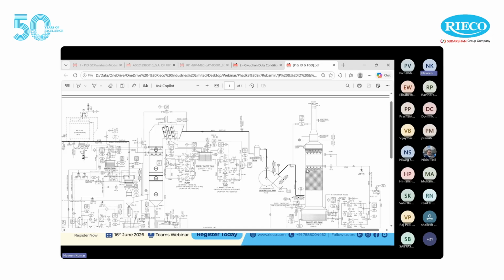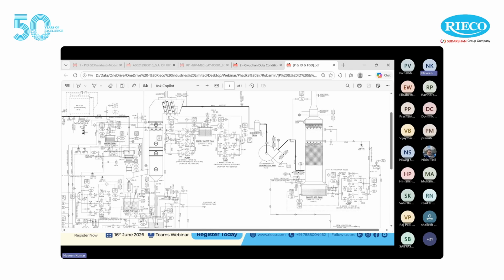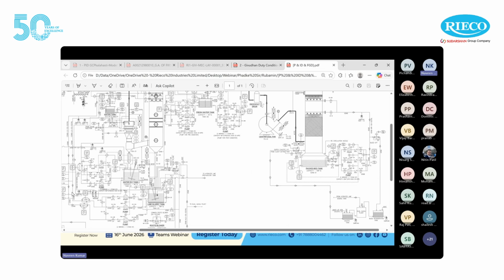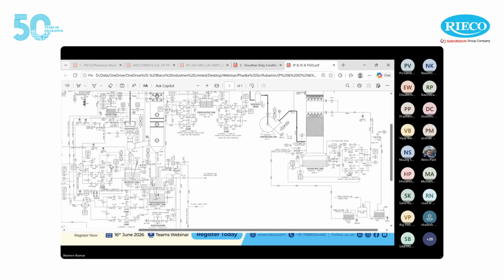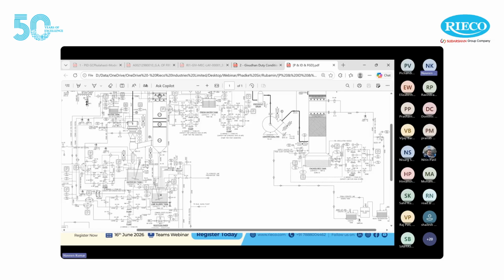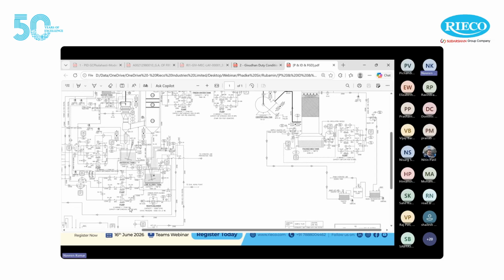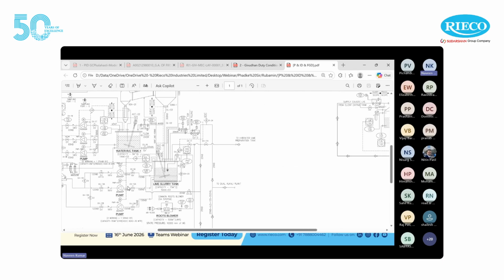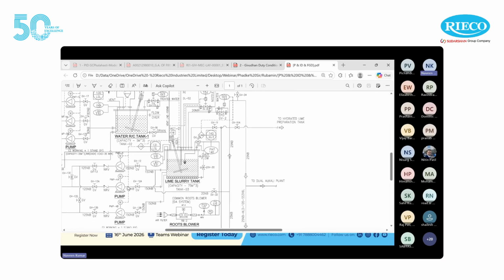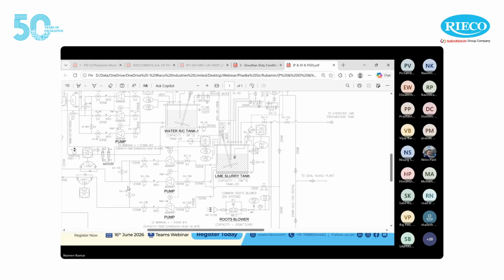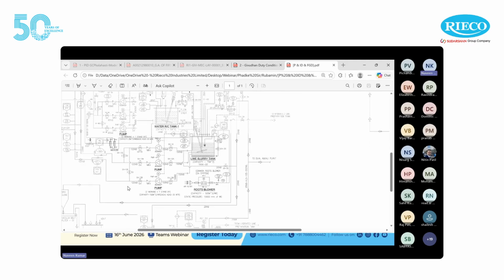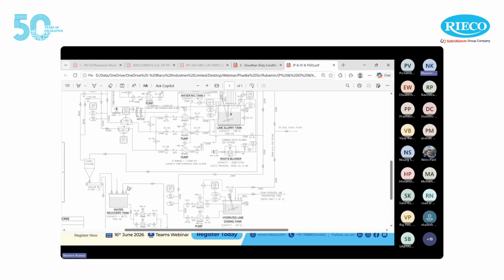Now, since we are using hydrated lime in this system, we have also got a post-oxidation step in the recirculation tank below the absorber, wherein we convert calcium sulfite to calcium sulfate. And so the gypsum produced can be used as a byproduct and can be sold to the cement plants. And there is no landfill to worry about. So we use a vacuum belt filter along with a hydrocyclone for separating out gypsum.